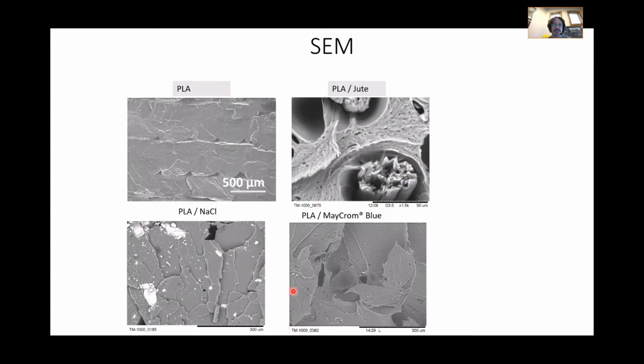Here's some scanning electron micrographs, or SEM micrographs, of some of this stuff. PLA printed very well on its own. If I were to do some failure analysis, I'd say this is a brittle fracture mode. We don't see that much evidence of plastic deformation. There's evidence of craze cracking, which is the primary failure. Anytime you take a piece of plastic and bend it and start seeing some white, that's called strain whitening, and that's a bunch of craze cracks forming.